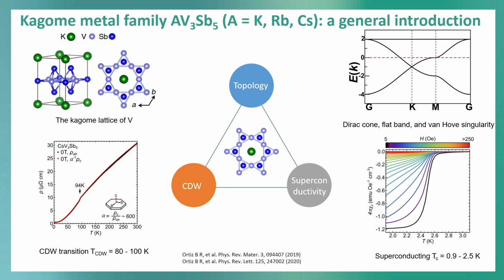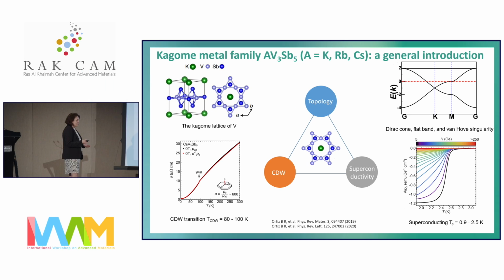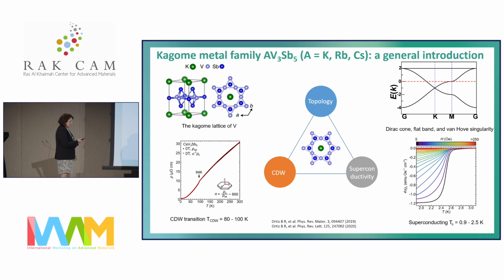So it's really interesting because we have here with the Kagome family very nice interplays, and there's another family which is even more interesting to other people, especially at UC Santa Barbara, and Tony, I think, is aware of the 1,3,5 compounds. It has not so many members like the 1,6,6 compounds, but it shows superconductivity already, and it shows charge density wave instabilities, and it shows even some anomalous Hall effect in the same compound, the cesium vanadium compound. So they are also extremely interesting because people think if we have a chiral charge density wave, symmetry is very low, a chiral symmetry, and superconductivity, we might have topological superconductivity, and it might be interesting for Majorana fermions or some interesting topological quantum computing.